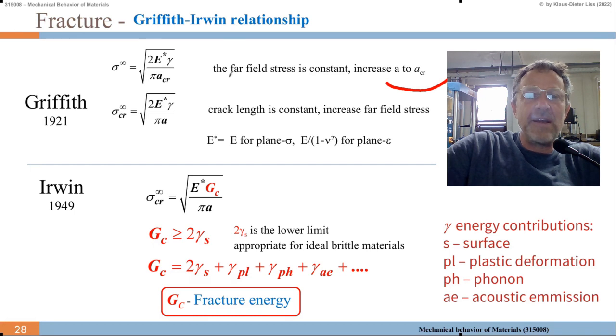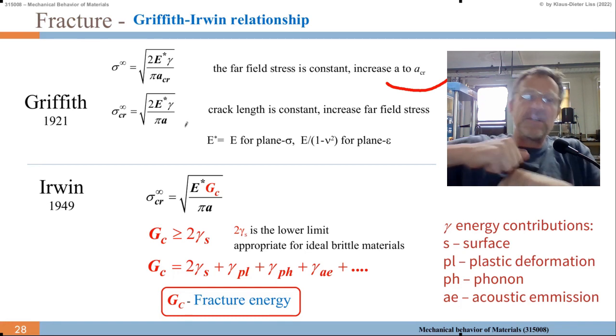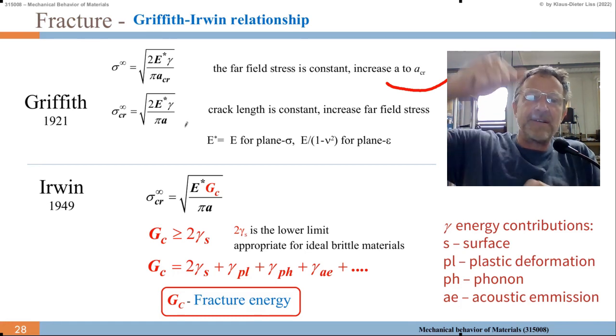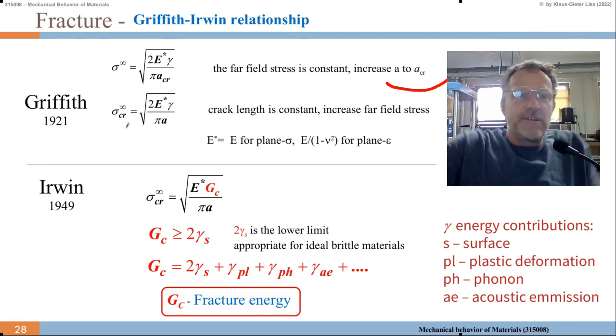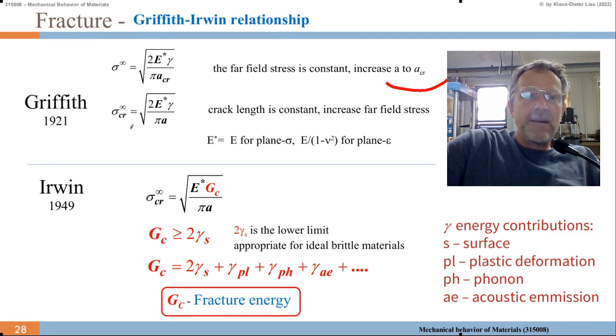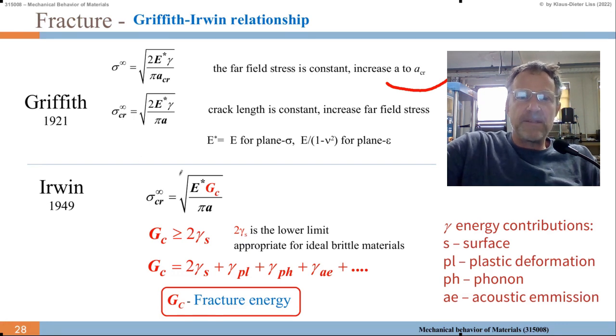In the Griffith theory, we can have two situations: the far field stress is constant and we increase A to some critical value, or the crack length is constant and we start from zero stress and increase the stress until we reach the critical stress where A starts to move, to yield.